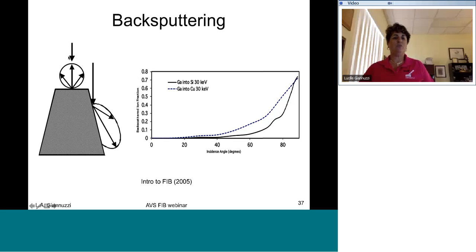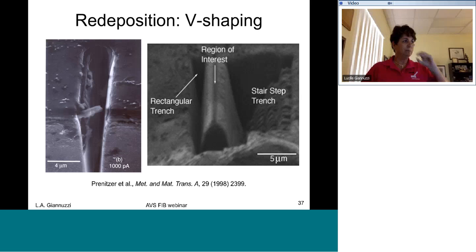Almost 100% of gallium, or xenon for that matter, coming into a sample normal to the surface will be implanted. But the sputtered particles coming out will come out in a cosine distribution. Conversely, if you're on an angled surface, almost 75% of the incoming ion will also come out. This is what this shows. So this is a really good indicator. If you see a high amount of gallium in your TEM samples, for example, then this is due to redeposition effects and not due to the basic ion-solid interactions, and I'll show you some of that later as well.